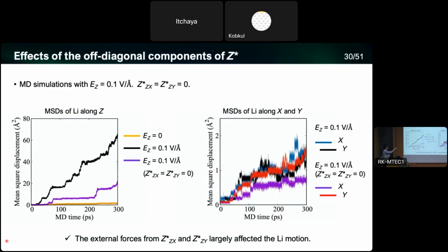So we artificially set these zx and zy as 0. Then what we obtain is the purple lines. The black line is the original mean square displacement under the electric field. But by setting these values as 0, the mean square displacement drastically decreased, which is still higher than the case without the electric field. And if you look at the mean square displacement along x and y, it's busy, but we can see the frequent vibration when we have all three components.